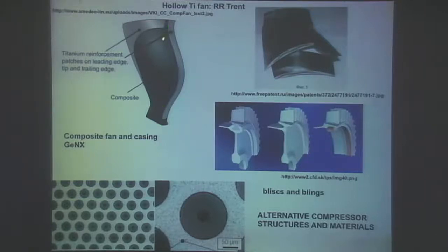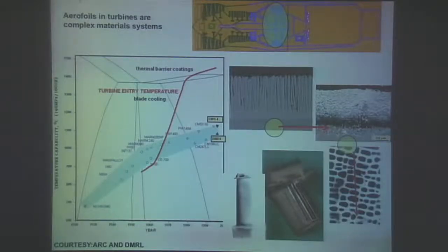Well, hollow titanium blades, for example, are used in the first stages of the Rolls-Royce Trent engine to reduce weight. The combination of titanium blades and discs in a welded form reduces the mechanical stresses of the dovetail joints that are present in conventional blade disc configurations. You remove the mechanical joints with welded joints so that you can save loading on this material, and then remove what is called the bore altogether by introducing titanium metal matrix composites in this ring, which looks like this. And so these are various alternative structures and forms of titanium alloys that we will evolve to in aero engine applications. But of course, the most critical material in aero engines is also nickel-based superalloys.